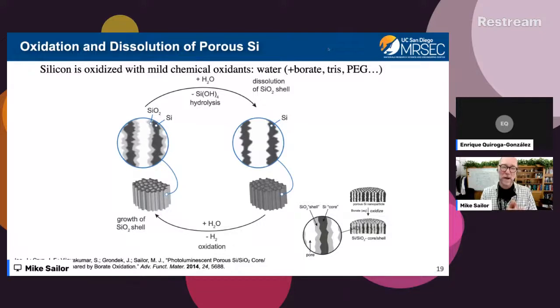So when that silicon oxide dissolves, it makes that byproduct, and it basically opens up the silicon structure. And then the bottom part of this slide is important. The silicon nanostructure, if it's made out of crystalline silicon, is readily oxidized. And so the silicon nanostructure will be oxidized by even a mild oxidant such as water or a buffer solution to grow that oxide. So you grow an oxide on the silicon, the oxide dissolves, and then you grow more oxide, and that oxide dissolves. And so you could go continuously through this loop, and eventually when you go around this cycle enough times, all of the silicon is dissolved away. But there are two features of this process. It's both this oxidation and this hydrolysis that are important for this reaction.